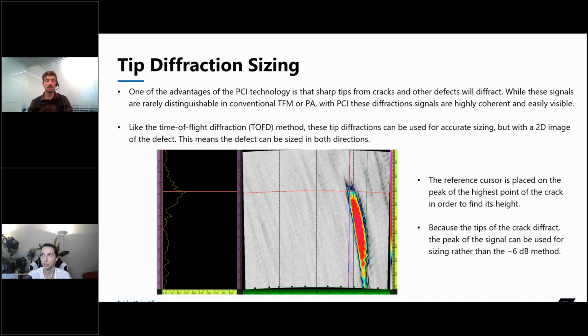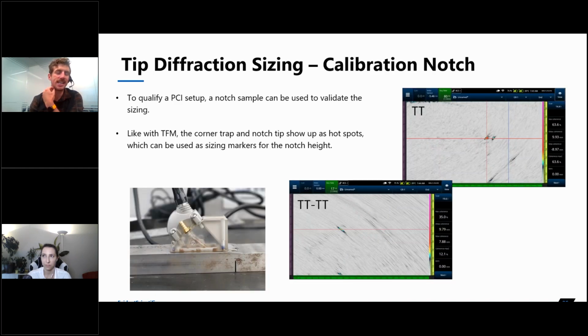PCI is going to be very similar, where we can actually see an increase in the level of coherence at the tips of our defects, but we don't actually have to change the gain in order to do any of our sizing. One of the ways that we can validate this, so this isn't necessarily a calibration, but more a validation of a technique before we do an inspection, is we can use a notch in order to verify that the velocity and all the other parameters are correctly set in order to size the actual notch itself.